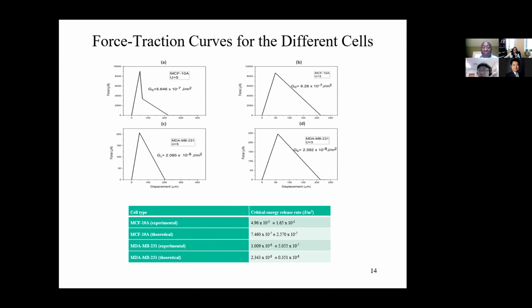And so out of these kinds of models then come experimental values of the critical energy release rate that are much greater than the theoretical values just associated with the cohesive tractions. And of course, the reason for the difference is because of the shielding contributions from the bridging protein structures. And the key result here is to say that the detachment of cancer cells gives rise to different interfacial fracture energies from those of normal cells.